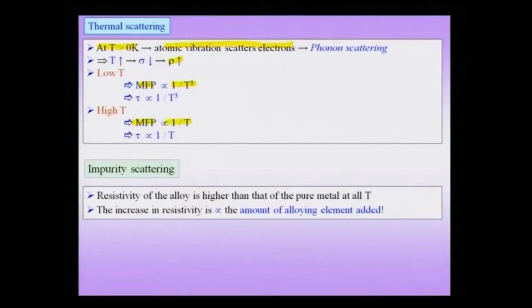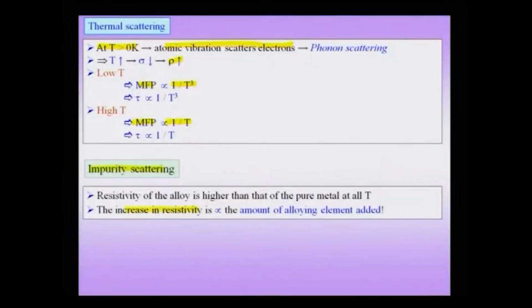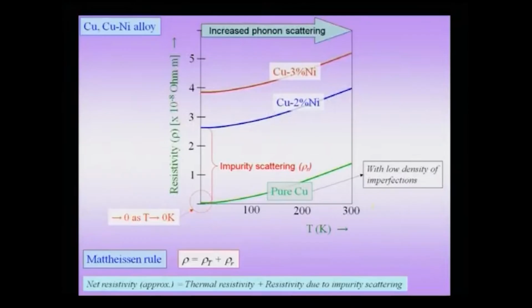And the other factor which we saw was the impurity scattering, and we said that the material with an alloying element or with an impurity is going to have a higher resistivity as compared to a completely pure metal. Now, the increase in resistivity is approximately proportional to the amount of alloying element added, and therefore, if I have a very pure material like copper with very low defect densities, and I plot its resistivity as a function of temperature, then I would notice